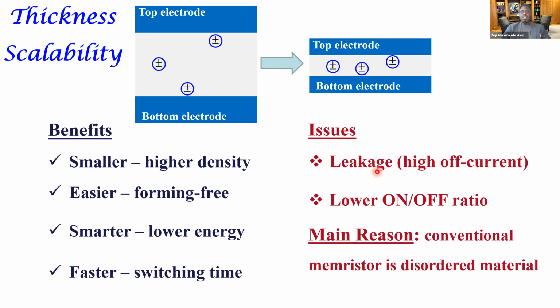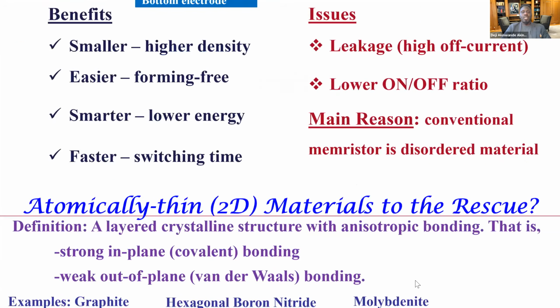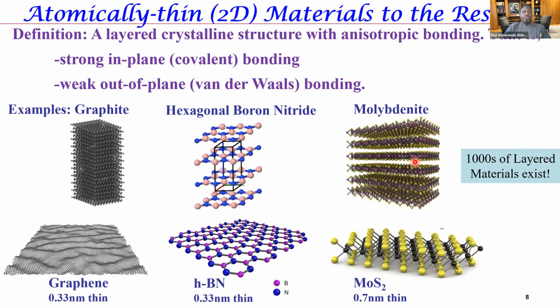The fundamental scientific reason is because these oxides or solid electrolytes used in these memristors are disordered materials, so there's just a lot of defects. When it's thick, it doesn't matter, it can still function, but when it's very thin, these defects dominate and you cannot control the phenomena. So that's exactly where I came into the picture.